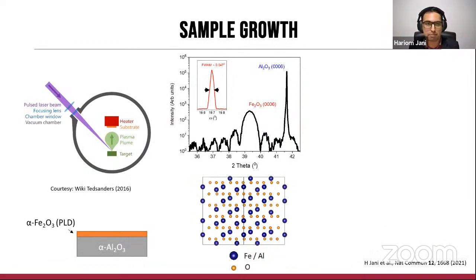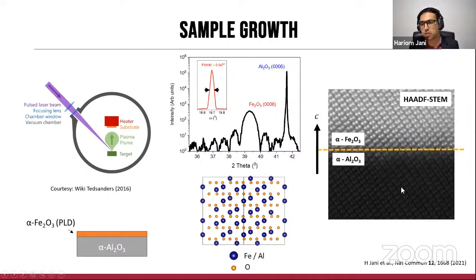Now, the samples themselves are grown by pulsed laser deposition, and this involves the growth of the functional layer on top of an appropriate substrate, such as sapphire in our case, which have very closely aligned structures. They're slightly off in their lattice parameters, which causes a slight strain, but because we grow slightly thicker samples, in the order of about 25 to 30 nanometers, all that strain is completely removed, and we actually almost retrieve back to complete normal bulk parameters of Fe2O3. These films are of extremely high quality as identified by the Laue oscillations, as well as the narrow full width half maximum peaks in the rocking curves. We've also done TEM analysis, which has revealed that these are very nicely structured.